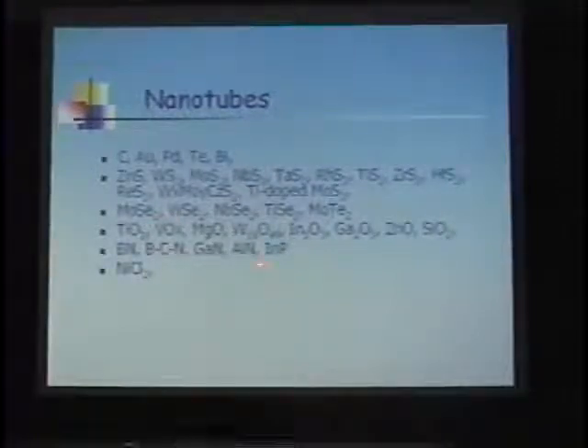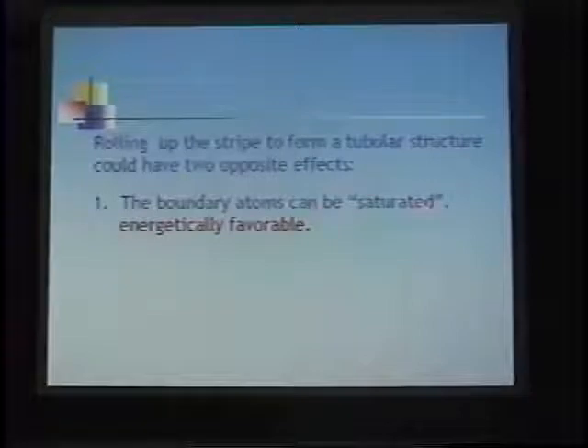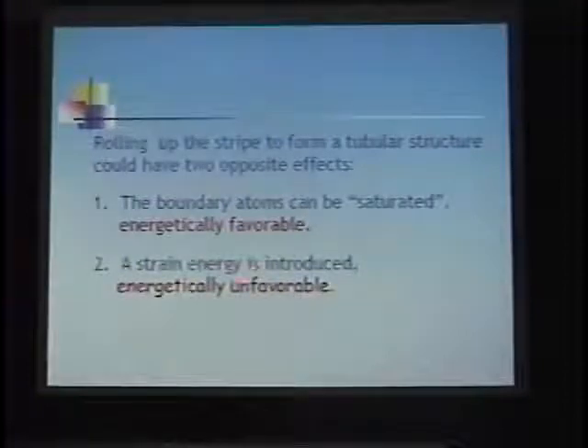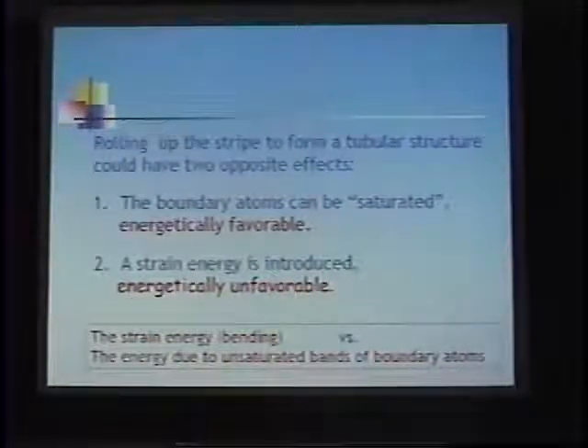You could see most of the nanotubes were constructed from layered compounds, with weak van der Waals interaction between the layers. As we know, rolling up a strip to form a tubular structure could result in opposite effects. First, the boundary atoms could be saturated. This is energetically favorable. Second, a strain energy is introduced due to bending. This is energetically unfavorable. So the final energy state of the nanotube depends on the competition of these two factors.